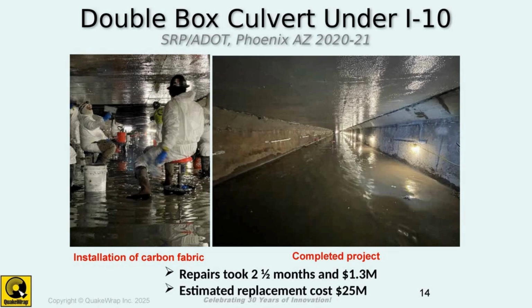And to remind you that strength-wise, we didn't have to put these 24-inch bands of carbon fabric. They could have easily gone every 30 or 36-inch on center, and that would have given us plenty of strength. But we wanted to protect the soffit of the slab with a layer of FRP, so there's no moisture penetrating into it, as a waterproofing membrane also. And that's why we decided to put these 24-inch bands with 2-inch of overlap along the edges. So as you see on the right, when the job is completed, there is no part of this slab that is exposed to the elements.